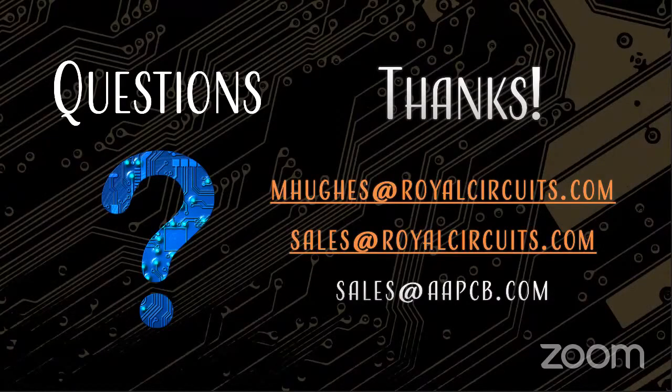Question is, with the sequential stack up, will that provide higher yields of the boards? And the answer is yes. It really comes down to registration. Well, it comes down to a few things. One, if you're doing sequential stack up, you can't etch interior layers after they've been laminated. You've got to etch them and then laminate them together. Well, one of the issues can be that, let's say you put these things in the high pressure press, and you can roll traces. You can cause traces to fall over if the aspect ratio is off. Okay, your board's done. We've got to throw the whole thing in the trash.